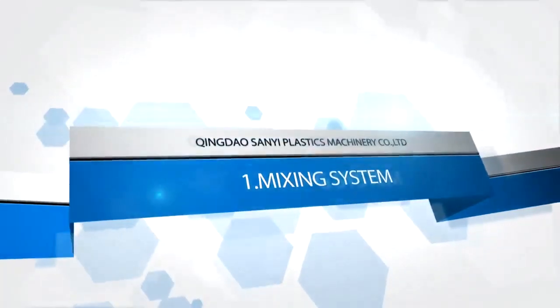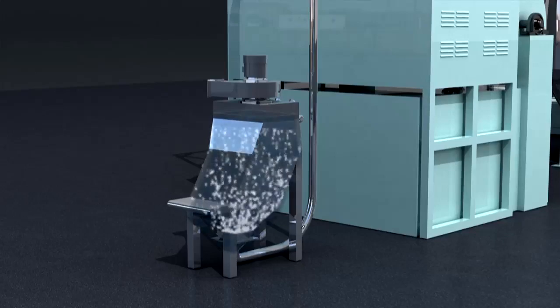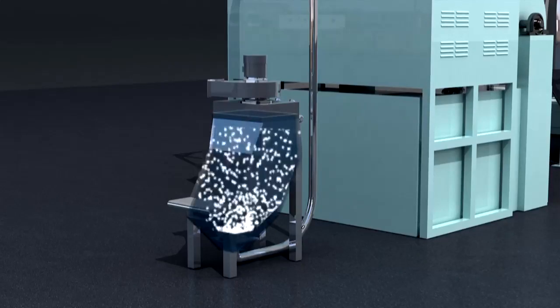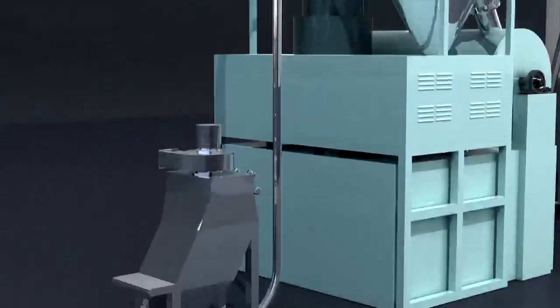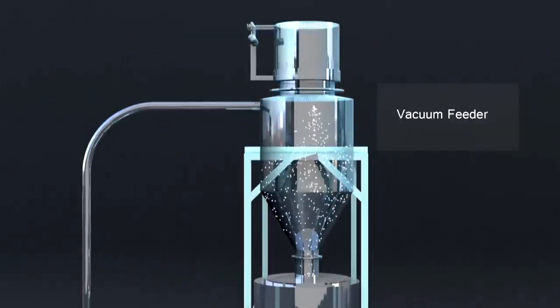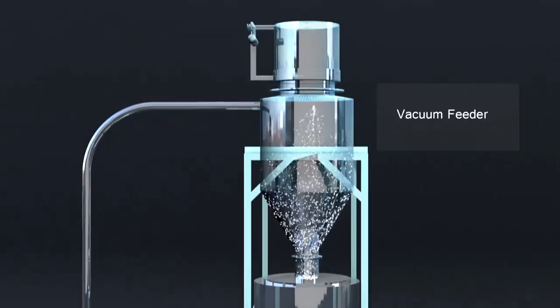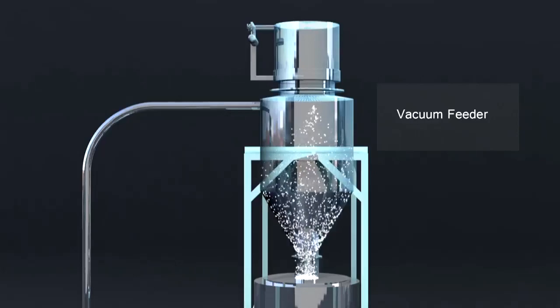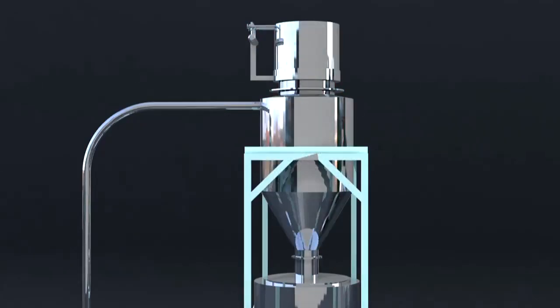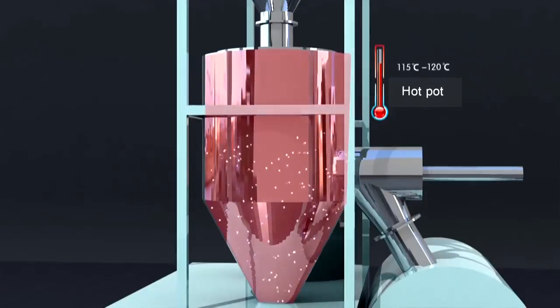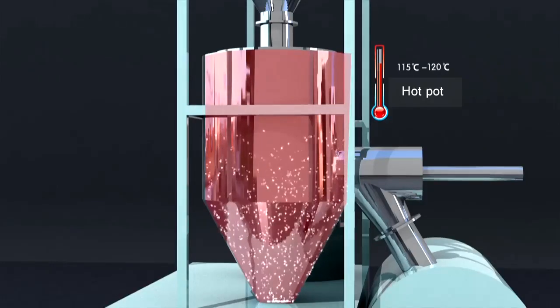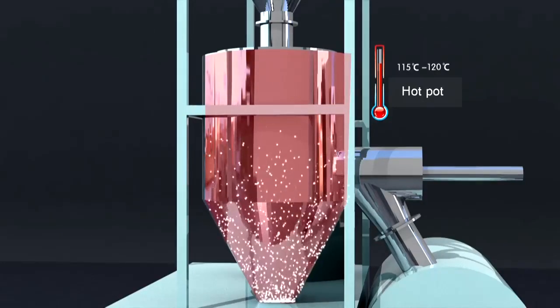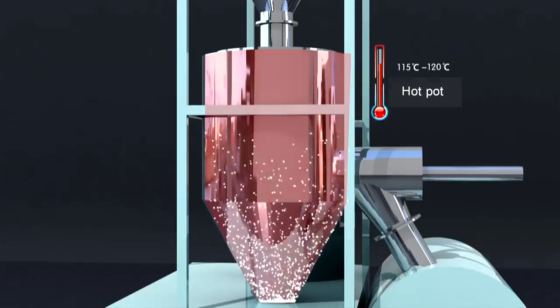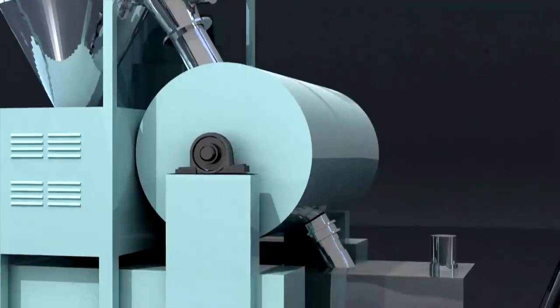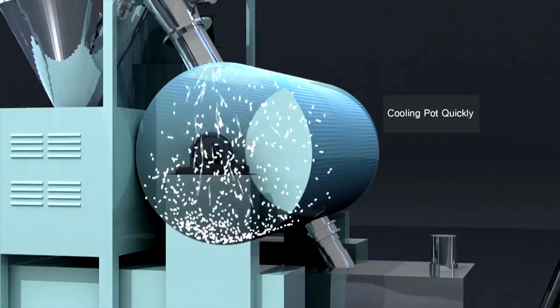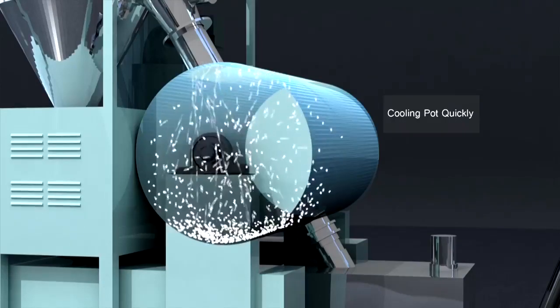Mixing system. Firstly, the material needs to be put into the feeding machine according to the formula ratio. And the material goes inside the mixer through the material loading machine. The material is mixed at a high speed through the friction heating principle, and the temperature is raised to 115 degrees Celsius to 120 degrees Celsius. The material is evenly stirred, and the water gas is removed during mixing.